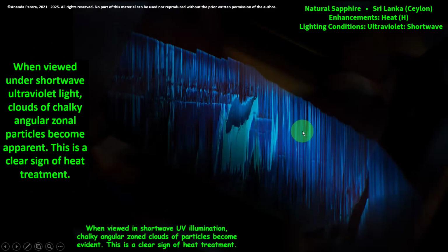This is the lighting condition here, ultraviolet short wave. We saw this in the cover photo. It is also a Sri Lankan stone, heated. When viewed under shortwave ultraviolet light, clouds of chalky angular zonal particles become apparent. This is a clear sign of heat treatment. It is heated stone.